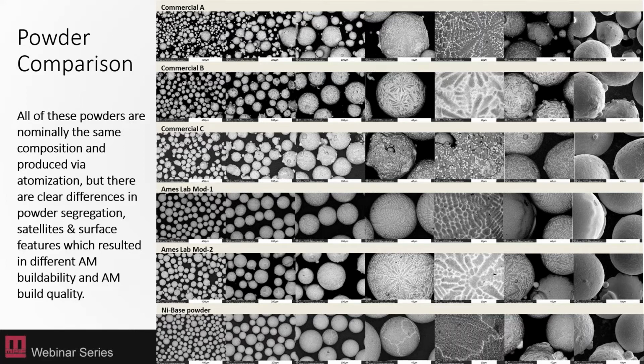and how those features are coming out on the surfaces, and whether or not they're large satellite contents or really nice spherical powders, affected the flowability and then the packing density of these powders in the bed, and then resulted in different AM buildability. So nominally, these are all the same size distribution and the same composition, but clearly the information on these powders is not captured just by those two criteria. So those are pieces that you may need to take into account when looking at your powder suppliers also.